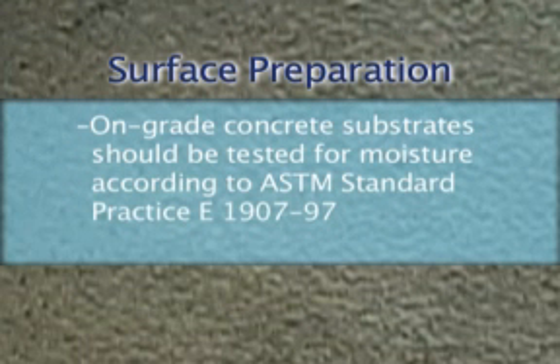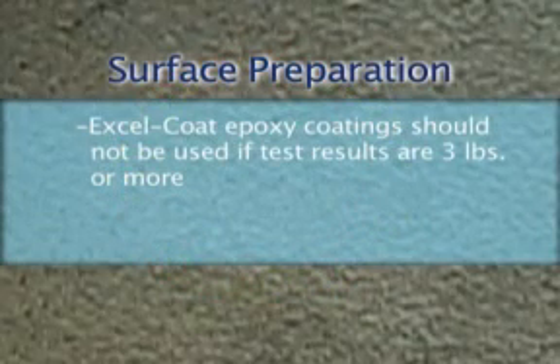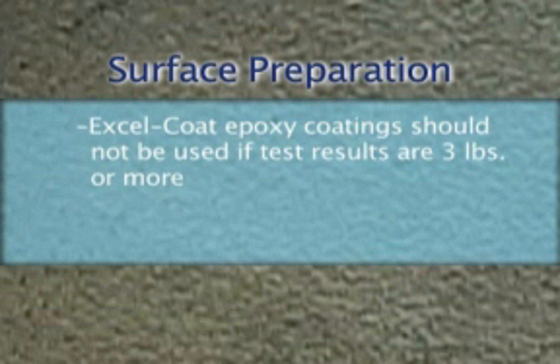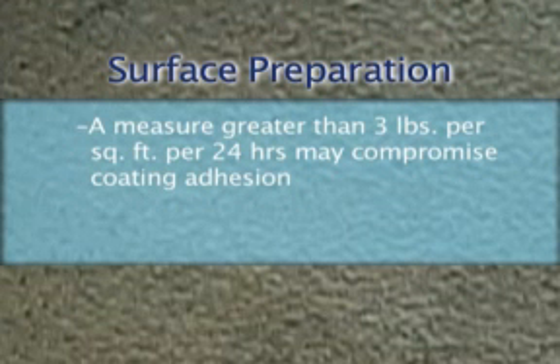Excellent Coatings recommends that on-grade concrete substrates be tested for moisture according to the ASTM Standard Practice E1907-97. Calcium chloride test kits are available from Excellent Coatings. Excel Coat epoxy coating should not be used if test results are 3 pounds or more. A measure of greater than 3 pounds per square foot per 24 hours may compromise coating adhesion.